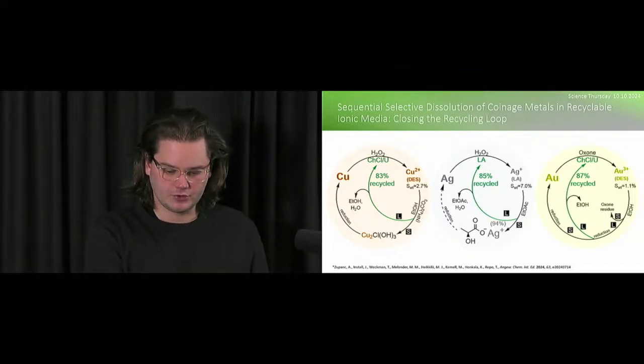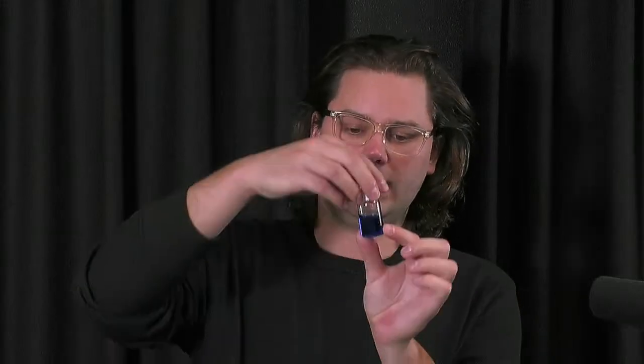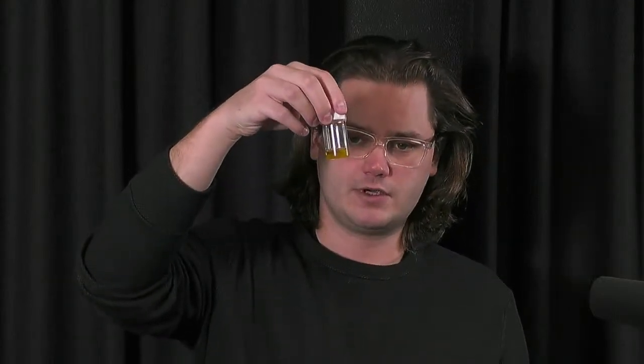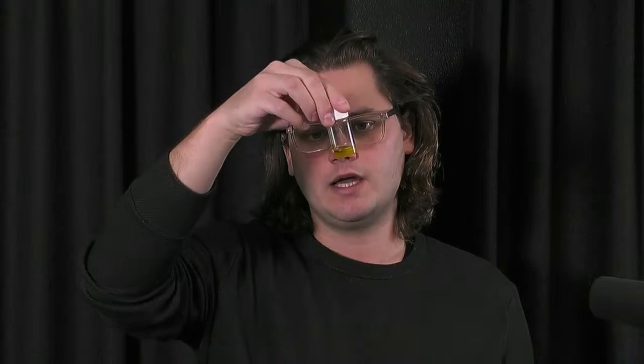I could show you now this. For example, this is the deep eutectic solvent that contains copper. It's this nice blue color. This blue color is very much known for copper 2+. For example, this is the deep eutectic solvent that contains gold. As you can see, it's a very nice gold color. So how we knew immediately that this is gold 3 is because it has this very nice gold color. So gold 3 cations usually have this very nice gold color, whereas gold plus is usually colorless.